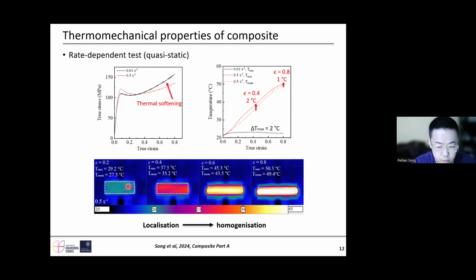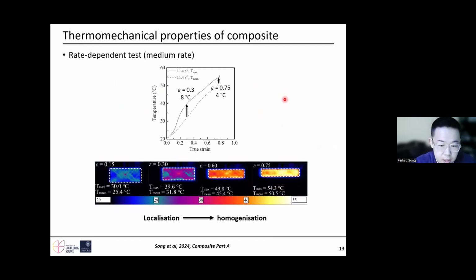Here is a continuous thermal image. I just put some here. We can see the strain localization, or temperature localization, at the beginning, and the temperature difference between maximum and mean is 2. At the end of this test, the difference between these two is 1 Celsius. Again, for the medium rate test, we can see the localization at the beginning and the difference between maximum and mean is 8 Celsius. At the end of this test, this difference is 4 Celsius. It is because this temperature was transferred to the surrounding material, and then we get homogenization in the temperature mapping.